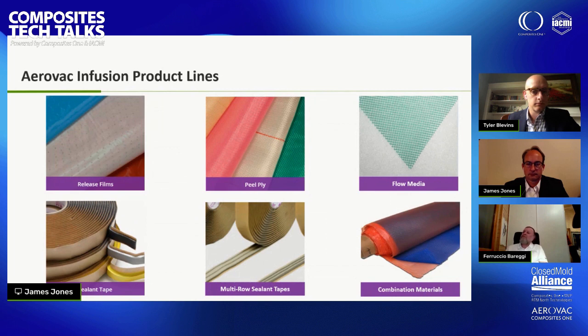So the other process material that is needed in the infusion of a wind blade is release film. Generally, the release films for wind infusion application are based on polyolefin, and can vary in thickness, generally from 30 to 50 microns, and perforation. Perforation is important, as it is the operation that lets the resin pass through the film and then infuse, penetrate, and saturate the laminate underneath.